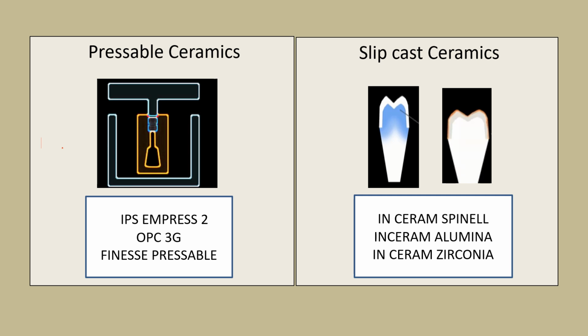Coming to the pressable ceramics, here you will have a wax pattern, and this wax pattern is attached to the sprue former, and this is invested in the phosphate bond investment. Later, the burnout procedure is carried out and that created this mold space. Then the sprue former and casting ring is removed and this investment is placed in a ceramic hot pressing machine. This machine will have a moving piston which moves the hot ceramic blocks into the mold space. That resulted in the formation of your ceramic crown. The examples are IPS Empress 2 and Finesse Pressable.